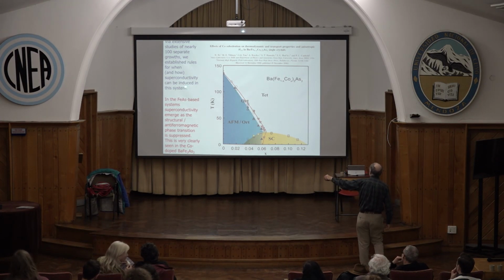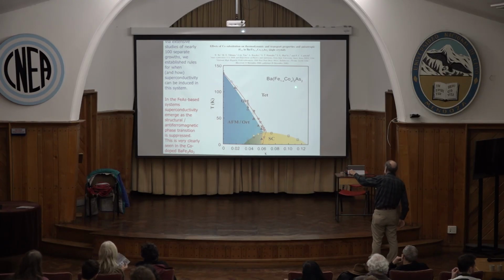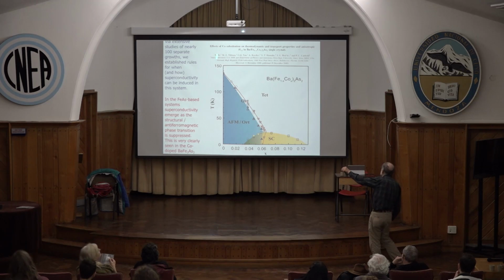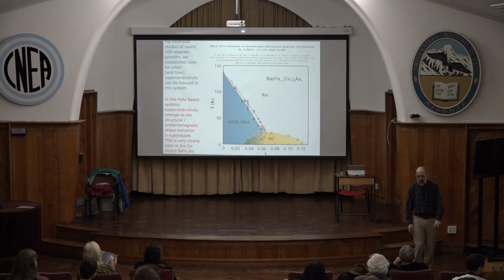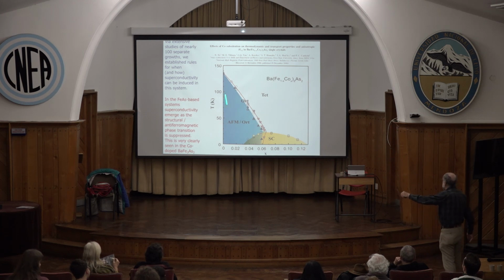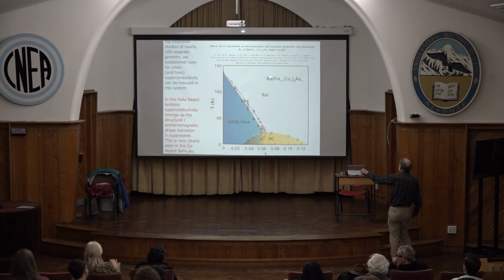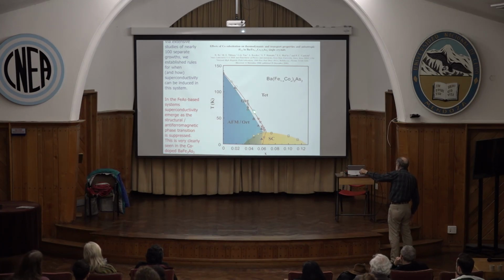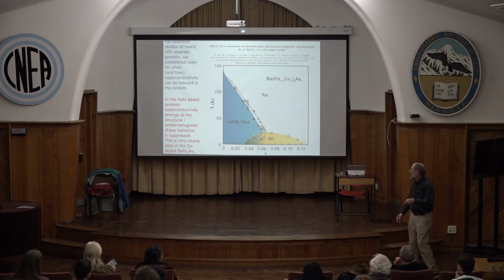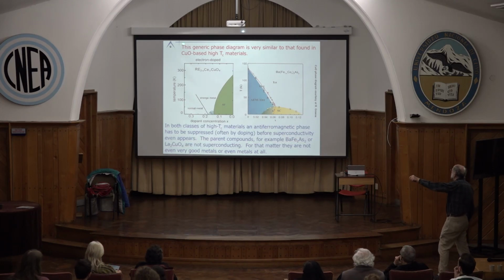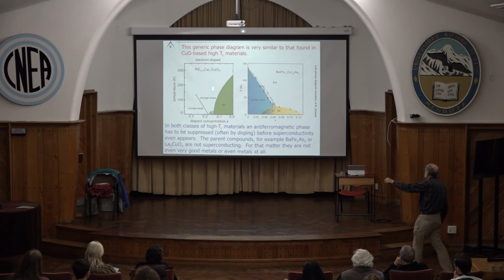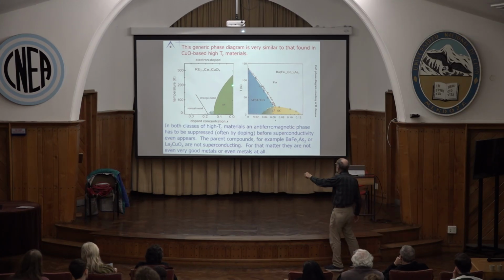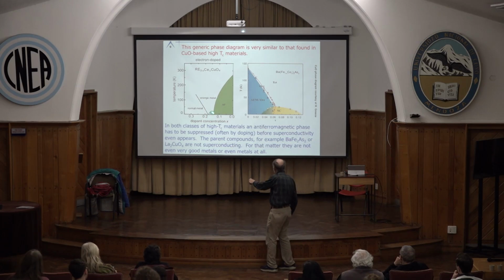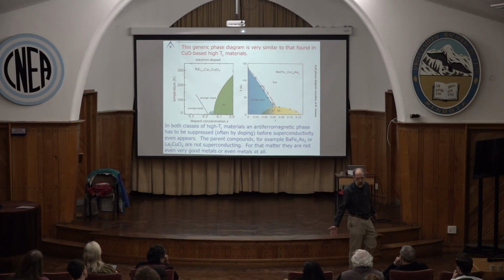So, with these iron arsenides, we did lots of different doping series to understand the rules. Pure barium iron 2 arsenic 2 is not a superconductor. It's just a crappy metal that has an antiferromagnetic transition. If you add a little cobalt and a little potassium, you lower the magnetic transition, you get a dome of superconductivity. Superconductivity is highest right where this goes to 0 at something that's called a quantum critical point. I point this out because this is darn similar to the cuprates.